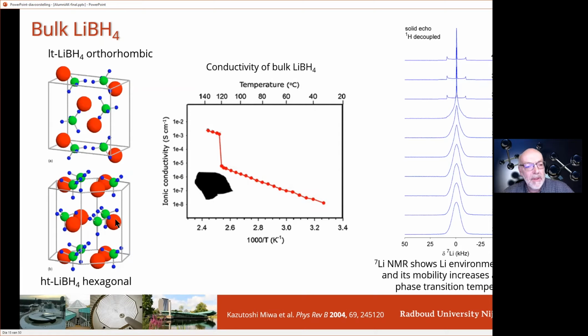But at higher temperature, you form planes of lithium through which the lithium can freely diffuse. And that we can actually see in our lithium NMR spectrum, which gives us a very broad line. But going to higher temperatures, we suddenly see a completely different spectrum. What this particularly means, I will discuss in a second. But the problem is, of course, that this phase transition into this usable phase only takes place at a temperature of above 120 degrees Celsius. So as such, it is much less useful.